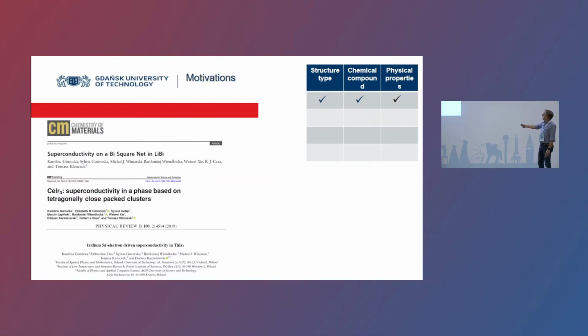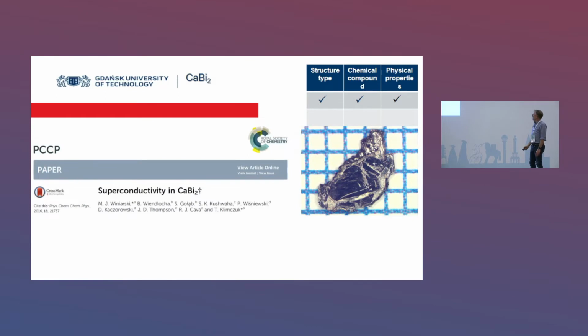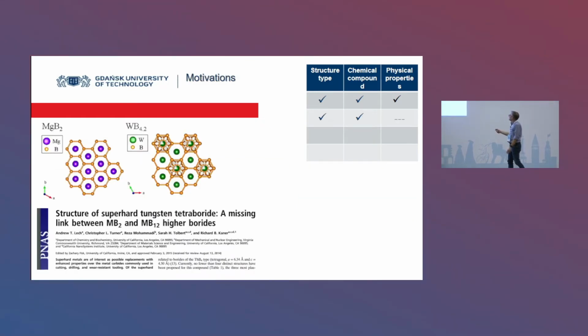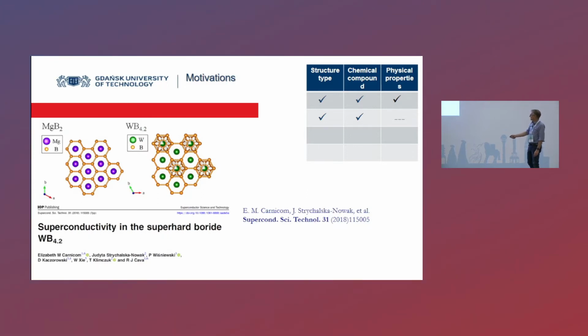Another 3 examples of this strategy, where everything is known, are lithium bismuth, cerium iridium 3, thorium iridium 3. So there are a lot of things that can be done with this strategy where everything is known. Another example, but now with the second strategy: the structure type is known, the chemical compound is known, and the paper is already published in PNAS, Proceedings of the National Academy of Sciences, and the title is Structure of Super Hard Tungsten Tetraboride. The paper was published by a UCLA group, and fortunately for us, they have not measured the low temperature magnetic susceptibility, and we found it's a superconductor, so the title is Superconductivity in the Super Hard Boride WB4.2.